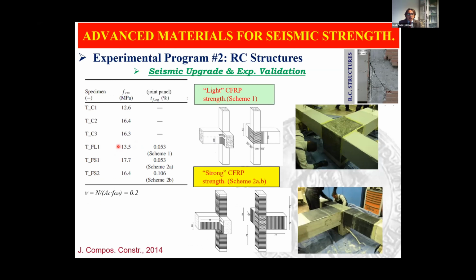2 classes of concrete, very, very poor, about 13 megapascal, and poor concrete, about 16 megapascal, and this is commonly found in existing buildings. And then we investigated the use of 2 possible scheme solutions. The light one with the quadriaxial carbon fibers applied just on the joint panel with only the connection made by U-wraps. And then a second solution, which is a little bit more invasive, but by also wrapping the columns, and this is done to increase the ductility of columns once the joint shear failure is prevented.